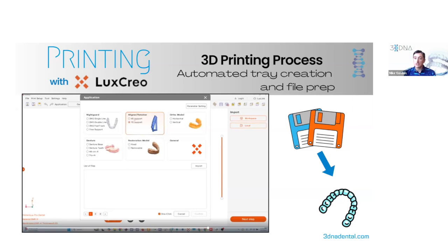But because LuxCreo's aligners are a thermoset, they have more surface area exposed than a traditional aligner because of the printing process, and because we are washing all that residual resin off of the outside of the aligner before we cure, there's just more surface area. So it's more important than with traditional aligners to clean them each day.